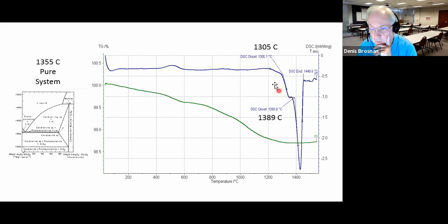Now this specimen was a little bit impure, and that's why these temperatures are a little bit lower than those indicated by the phase diagram. But what I'm trying to say is we begin to get melting at 1305 and melting in abundance at 1389 degrees here. And of course, the specimen melted entirely and then solidified. Please ignore the blue line because I was playing some games with some fluxes at that particular time. So 1355 in the pure system, but we're going to get melting temperatures below that in the real world.